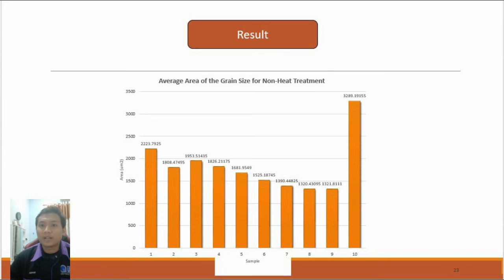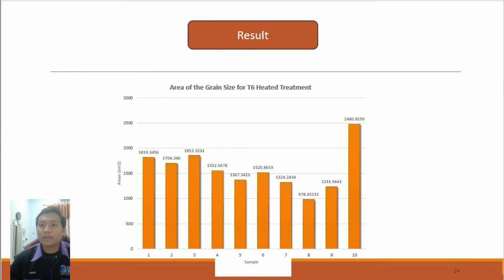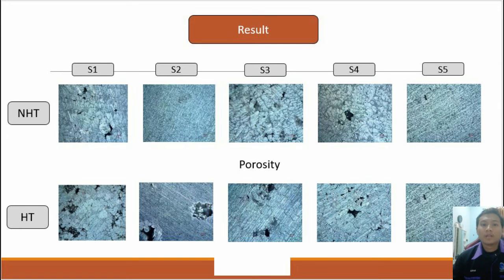Based on this graph, the largest area of grain is sample 10, while the smallest area of grain is sample 8. Then, this is the graph for the average area of the grain size for T6 heat treatment. The graph shows the largest grain size also on sample 10, which is the as-cast LM25 without modification, while the smallest grain size is sample 8, which is the modification of LM25 with 6% copper and 1.5% magnesium. Next, this is the visual for all of the sample surfaces containing the porosity defect.